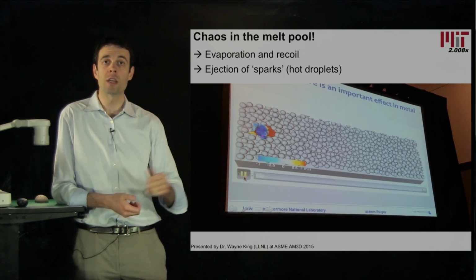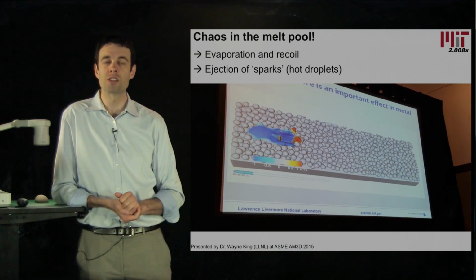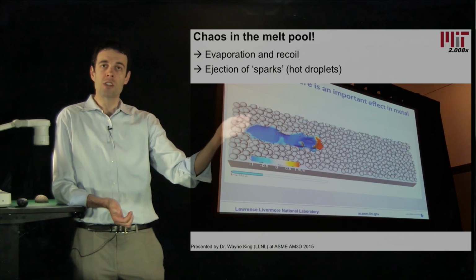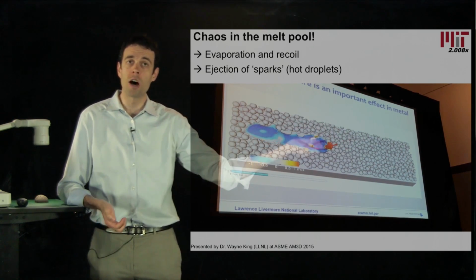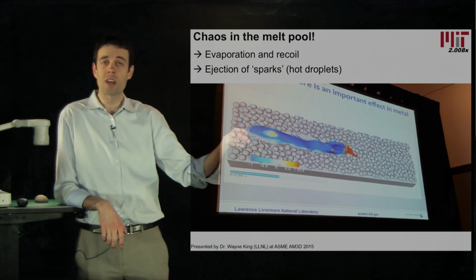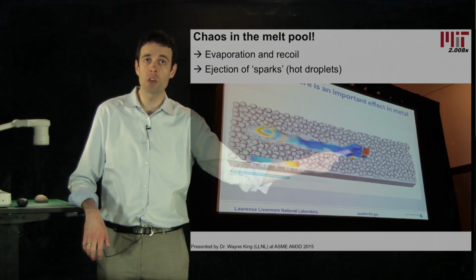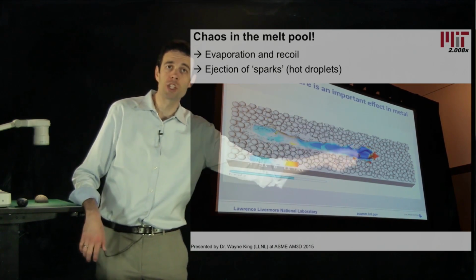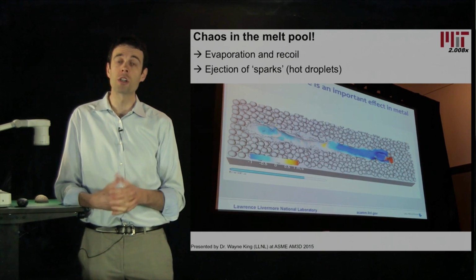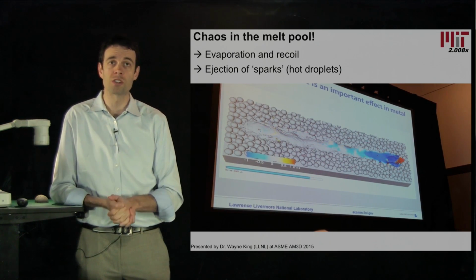I took this video attending a presentation at an additive manufacturing conference last year by Dr. Wayne King, who heads the simulation group in additive manufacturing at Livermore Laboratory in the United States. And this is a slowed down supercomputer simulation of the formation of the melt pool by the laser running over the powder bed. And you can see that it looks essentially like a boat going through water. The melt flow is extremely dynamic, and you may also see little pieces of material being ejected off into space. Those are the sparks that we see in a video of the SLM process. It's material ejection caused by the extremely rapid vapor flows and capillary pressures that exist at the surface.